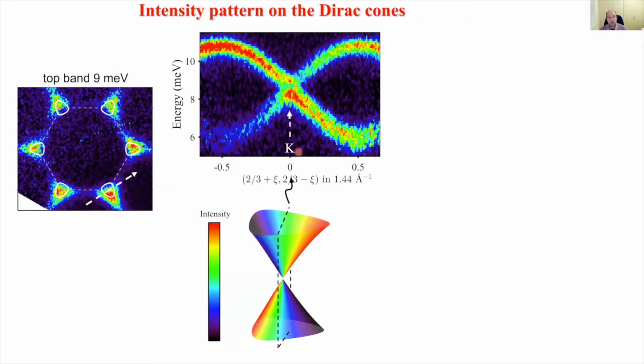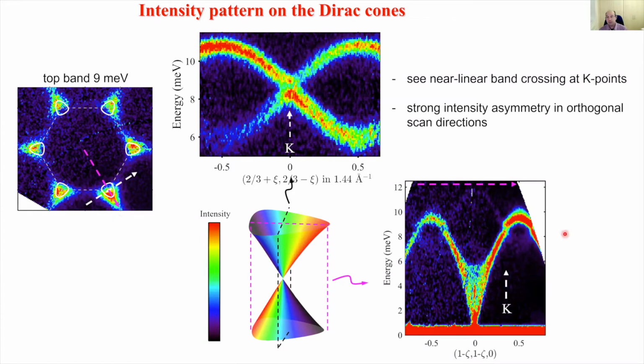However, if we were to scan along this direction, which corresponds to the radial direction out, then what we see experimentally is just a single mode, this one going out there. There is another mode out here, but this has zero intensity. Okay? There should be another mode here, but it has zero intensity. And that's indeed as expected theoretically. There should be no intensity on this side, but all the intensity should be on this side.